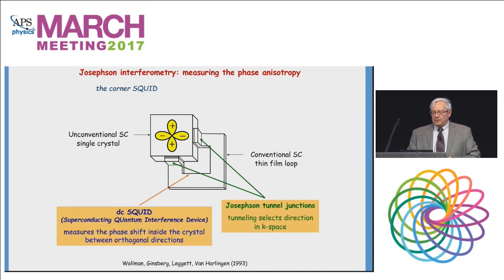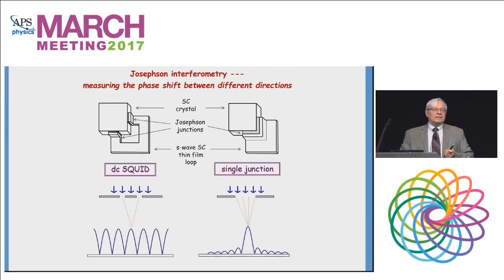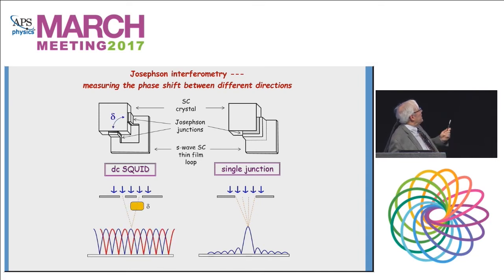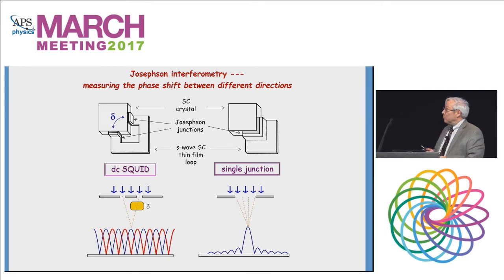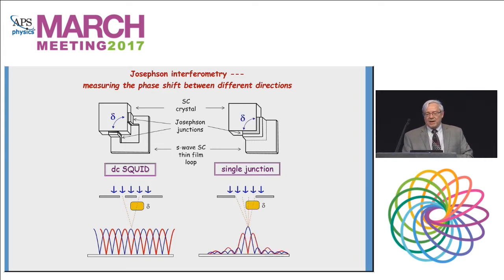You form a DC SQUID. By looking at the properties of the SQUID, you can determine whether there's a phase shift in the quantum material. You can think of this in analogy to single slit interference. If you have a SQUID, if it's an S-wave, you'll get a periodic modulation. If you change the order parameter in part of the junction, just on one face, then you can see the fringes shift.